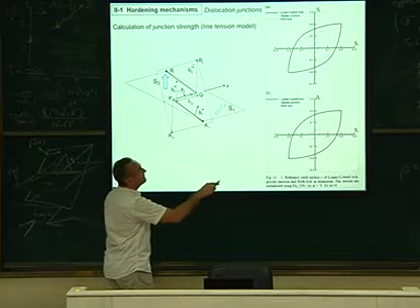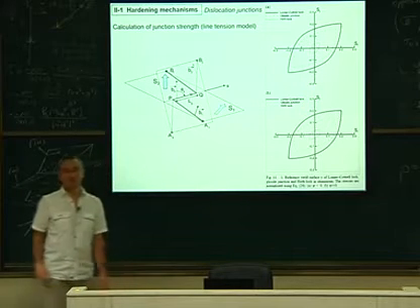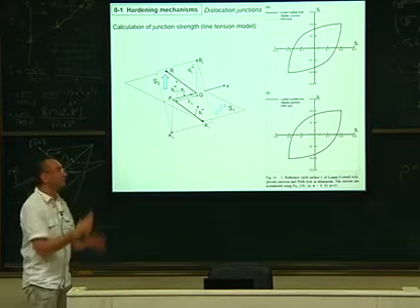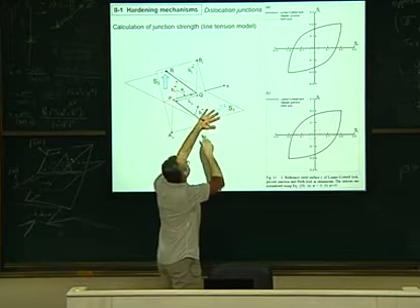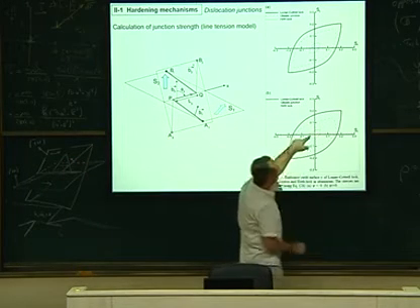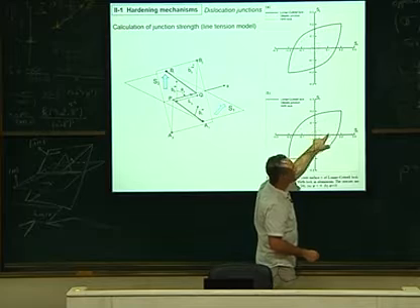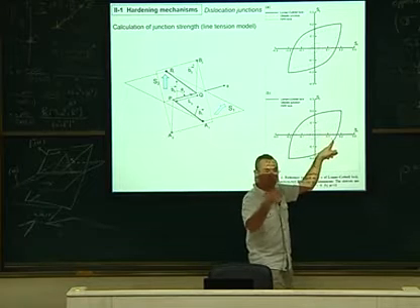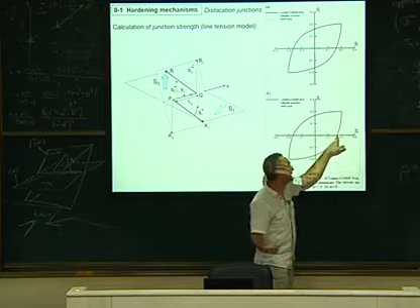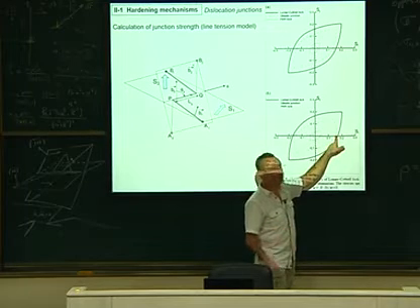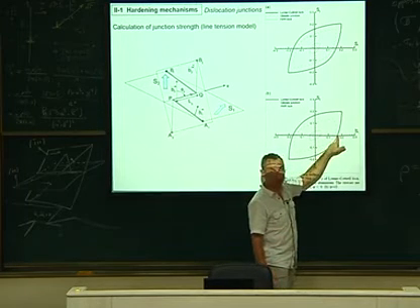So this is my S1, my S2. Those are the two stress quantities, two shears that I can plot. Typically, if I apply a pure shear here and zero stress there, I will move on a curve like this. This will move my junction a bit. It will be moving, and at one point the junction disappears, is broken. So I save the point, and this gives me a point here on the line.